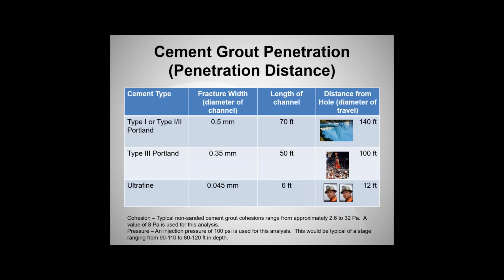Essentially, when you get into matrix porosity and very small fractures, you may have to go to a solution grout to get the grout to penetrate. Then, depending on the size of those apertures and the hydraulic conductivity, the viscosity is going to dictate whether or not you can economically push that grout into the ground.